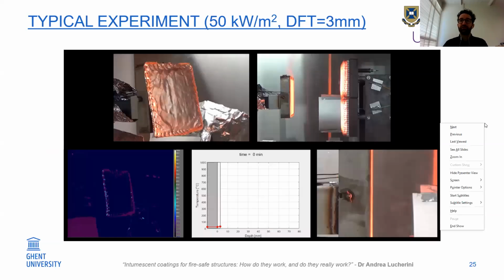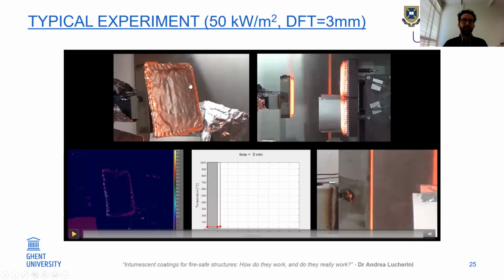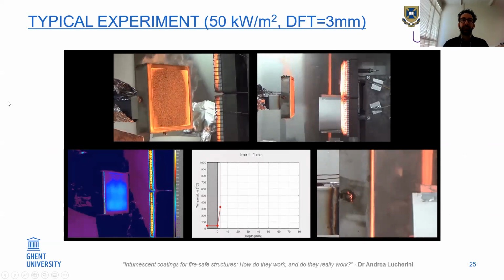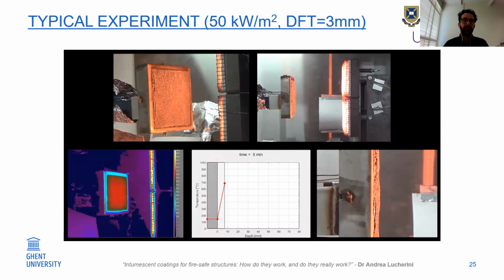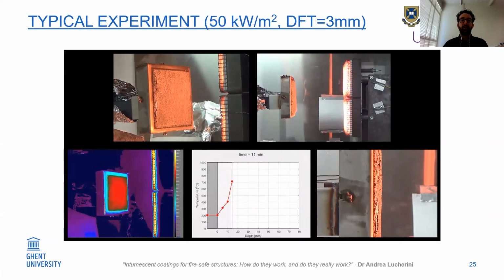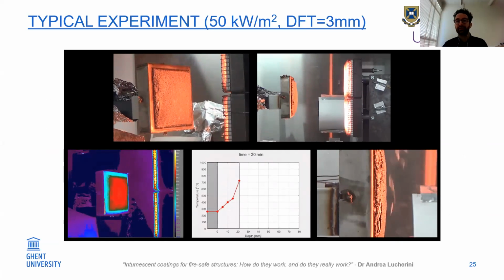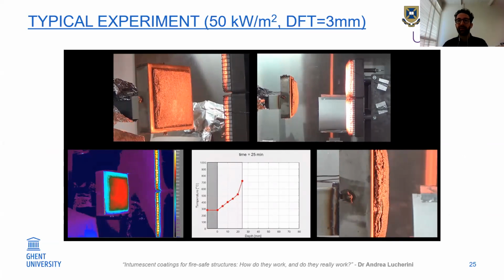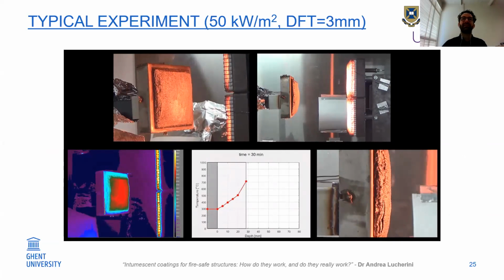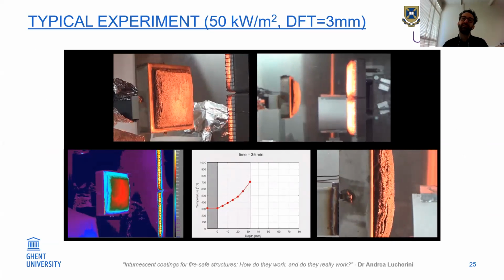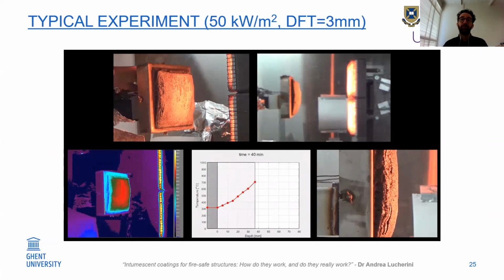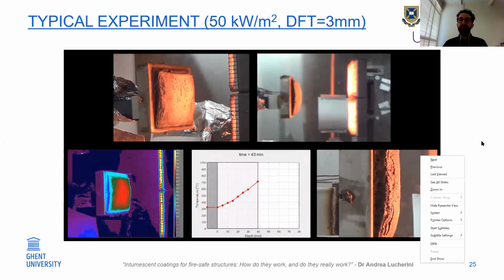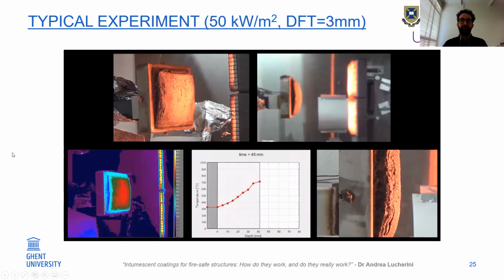Here, what I want to show you is a typical experiment that you can see at the top. You see the recording of a normal video camera. On the bottom left, you can see the thermal camera image. On the bottom center, you can see the temperature in the steel and inside the coating. And on the right, you can see the swelling of the coating during the experiment. This is the case of 50 kilowatt per square meter. The test was 1 hour. You can see the time here. And, oh, sorry, I stopped it.